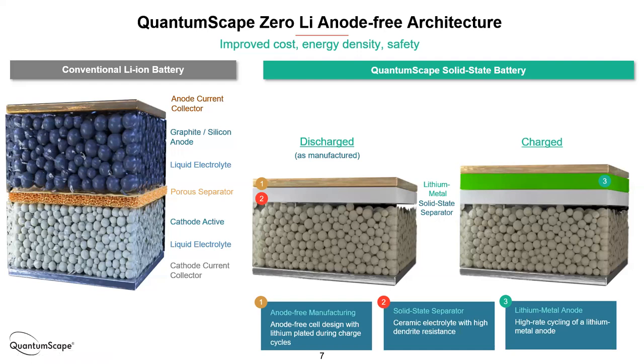We basically drew it to scale here. It's between 30 and 40% more dense for the same cathode material. So that's obviously beneficial to energy. There are a few other advantages. Because we don't have to make an anode, we've eliminated the material that's required and the manufacturing cost for 1/3 of the whole system. So there are some benefits there to cost. It turns out that there are also benefits to rate. So I mentioned earlier that the rate limitation is often due to the lithium ions having to enter this host material. So now we've gotten rid of that host material and we have just a single interface over which we have to transfer lithium ions. And so if you make that interface efficient enough, low enough resistance, you can overcome some of the power challenge as well.